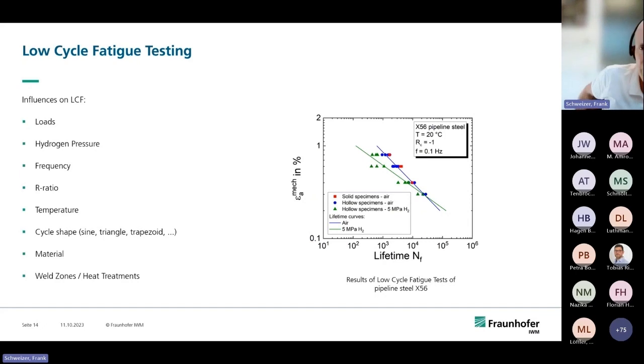But you can also use this diagram, for example, to do your calculations for the mechanical part of your caverns. You have a lot of influences for the low cycle fatigue: the loads itself, the pressure. The more pressure you put in, the more pronounced is the reduction here. Test frequency is very important. As I said, you need to give the hydrogen enough time to diffuse to the process zone in the steel. Temperature, for sure, is changing the outcomes. And as I said, you always have to test all zones in your material.